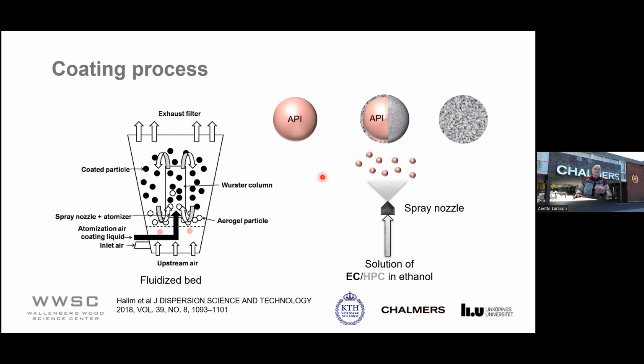So if we take it a little bit slowly here, so here, oh, that was not so slow, but here it is when sprayed, so the pellets get a shower, and then they are wet here, and here they dry. Since the air stream here is high, you can control the temperature of it. So you have a drying of the droplets that have now been on the wetted surface, and they must be dry. The pellets must be dry when they come here, because then they will come in contact with other pellets. And if they are not dry, they will glue together and you will get twin pellets, and that is not good at all.